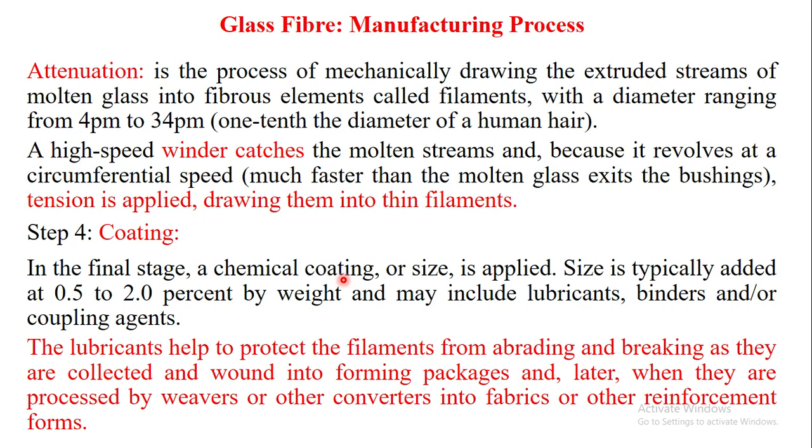Size is typically added at 0.5 to 2% by weight and may include lubricants, binders, or coupling agents.